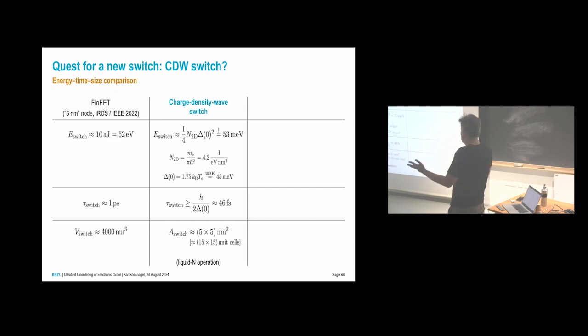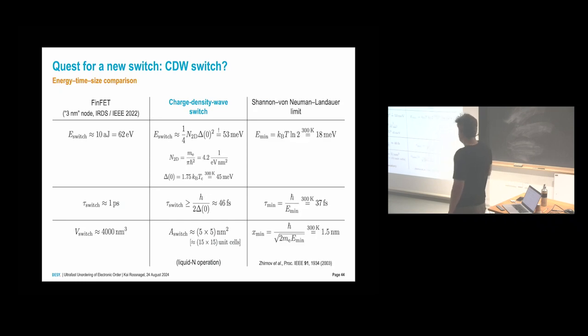Okay, this you can compare to current technology: switching energy, 10 attojoule. This sounds low, but it corresponds to 62 electron volts, and this is huge compared to this. Switching time is also longer, and at the moment you have a volume of this fin in your FinFET of about 4,000 nanometer cubed. And this is the fundamental limit.